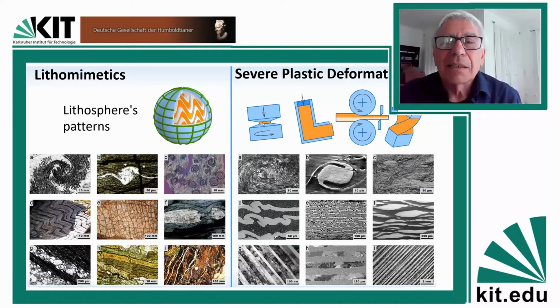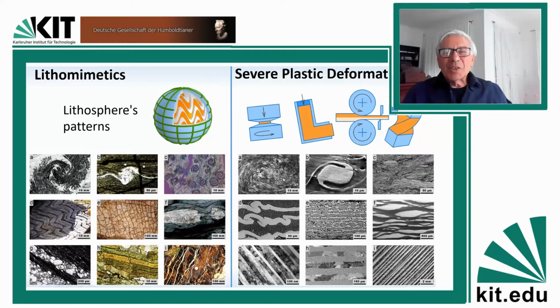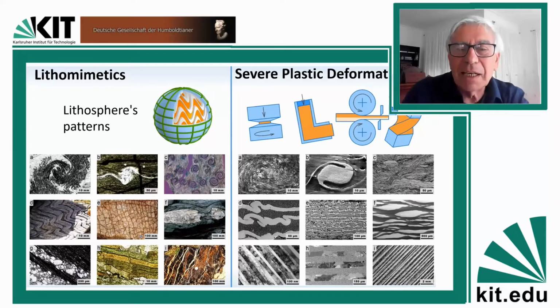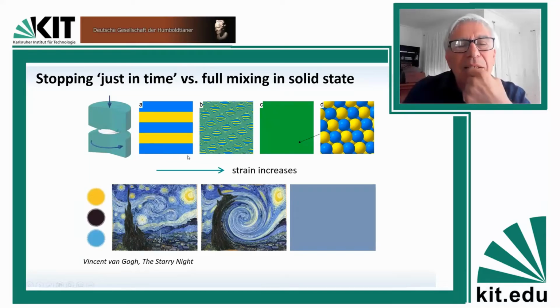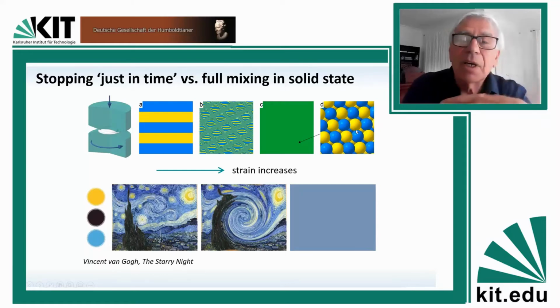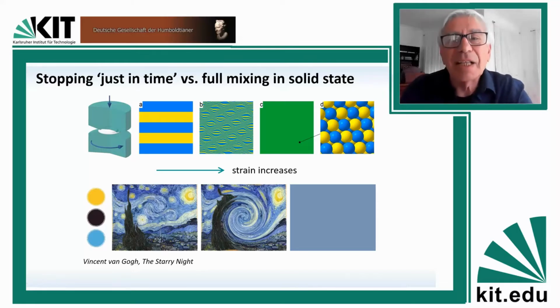Now, at KIT, the most popular technique is this one, high pressure torsion. And the structures that were produced are, for instance, like this one. You take two materials, you co-deform them together, and you obtain a rather complex structure. It is shown here as an idealized picture where you have two different materials. You do this high pressure torsion deformation. You break down the layers into a pattern of this kind, for instance. And if you continue, you go on and on, you could even get almost full mixing at the atomic scale. So that is something that would be desirable if you want to produce an alloy by this mechanical alloying in the bulk.